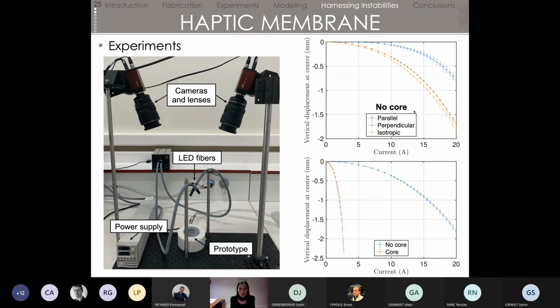Another thing is that when we add a core, we are going to concentrate the field really next and close to the layer, and we manage to get vertical displacement or deflection around 2.4 millimeters at the surface of this layer. And what's interesting to note is the current that we have to input in this small device comes down to 2.5 amps, which now actually makes the possibility of proposing actual devices that are manageable in terms of power consumption more realistic. So that's what the experiments show.